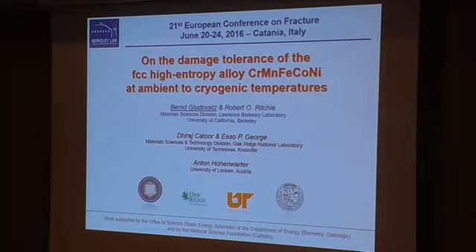At the intersection with the blunting lines, we measured at room temperature a fracture toughness of impressively 220 MPa root meter, which, and this is the nice thing about this material, remains stable, high, down to liquid nitrogen temperature, where we measured essentially the same fracture toughness. We have to keep in mind that at the same time strength and ductility go up.